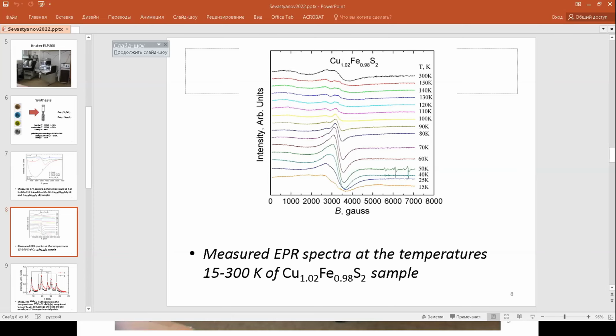A distinctive feature of the EPR spectra of the Cu1.02Fe0.98S2 sample is the almost complete absence of an intense signal of ferromagnetic nature in the entire range of temperature studied. At a low temperature, a signal with a g factor of g equal 2.08 is clearly visible. Its intensity and the shape of the line change as it heats up to room temperature.